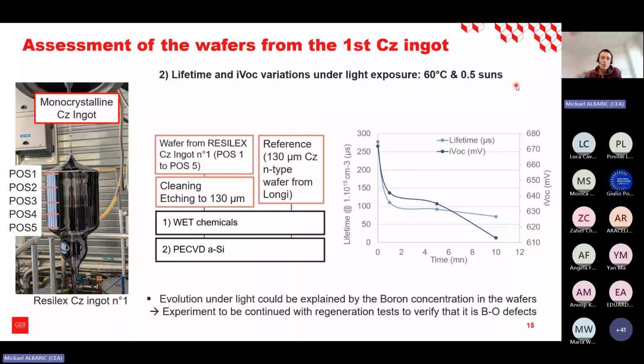So this evolution can be explained by the presence of residual boron concentration in the wafer. And when there is some boron in the wafer and oxygen coming from the crucible, we can generate boron-oxygen complexes that, under illumination and under temperature, can reduce the quality of the wafer. This is a light-induced degradation.